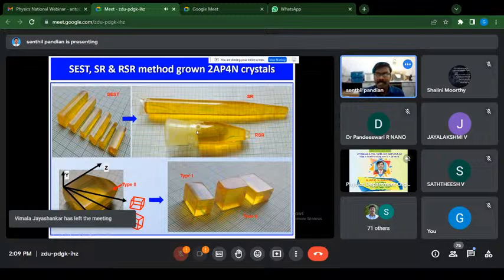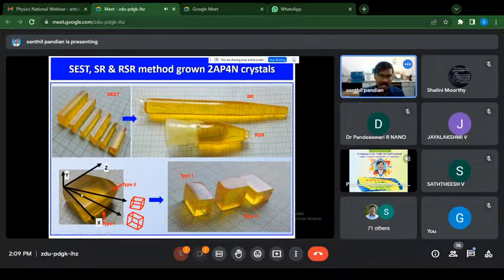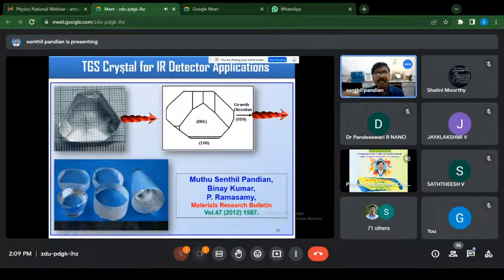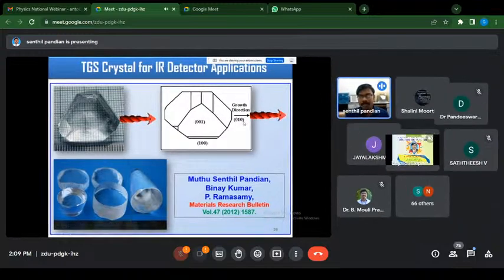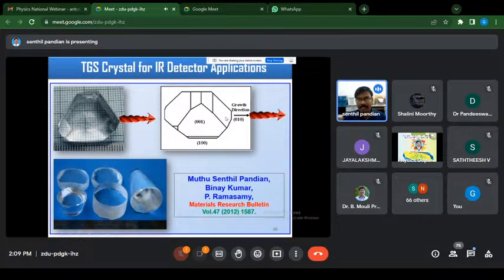We have also checked the crystalline perfection using HRXRD measurement. The single and sharp peak we have achieved in this RSR method compared to the SR and SEST method. So this is the ACRT method grown the same 2AP4N nitrophenol derivative single crystal, and we have successfully fabricated the type 1 and type 2 SHG elements here. This is the TGS single crystals for ferroelectric application. As I told you, here we can use this 010 polar B direction for this ferroelectric application.